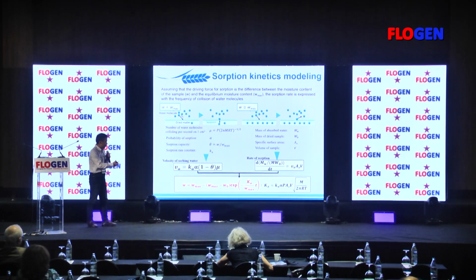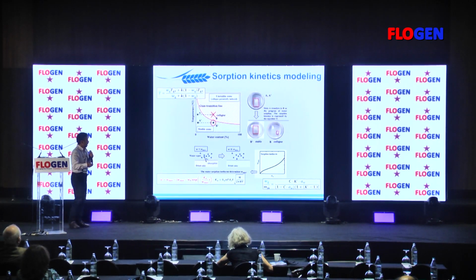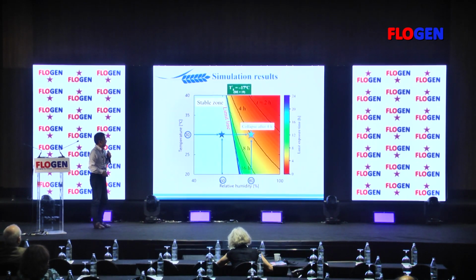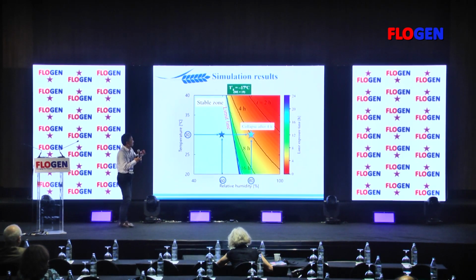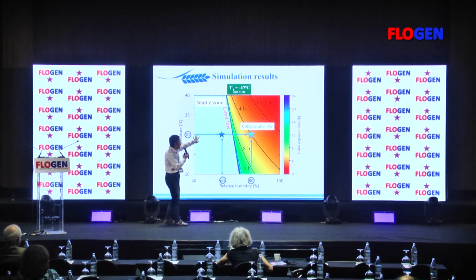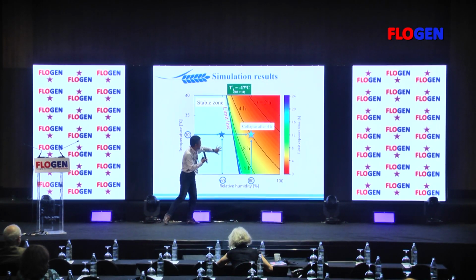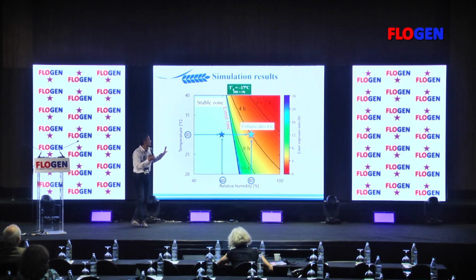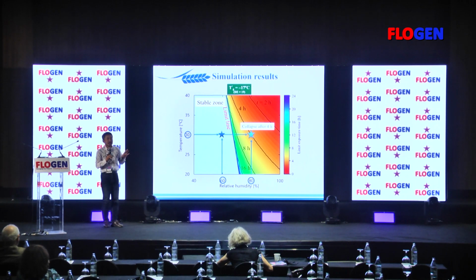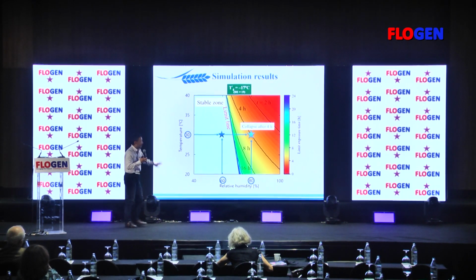Then we combine it, and we can get this equation. The equation with the red color is our model. So let's calculate. Combining these three relationships all together, this is the result. If we place our matrix in this zone, it doesn't make the humidity-induced collapse. It's determined by the glass transition property, but it's okay.